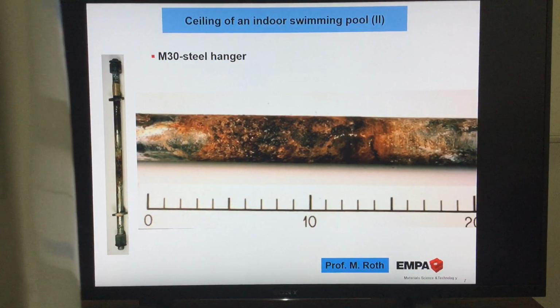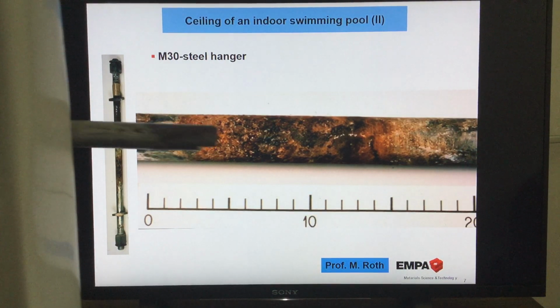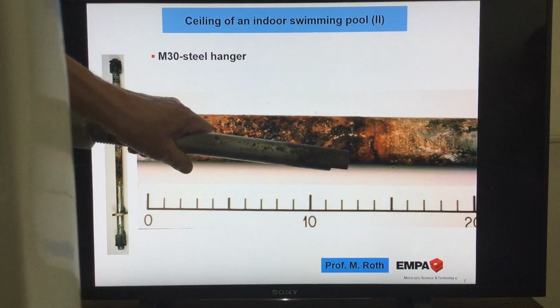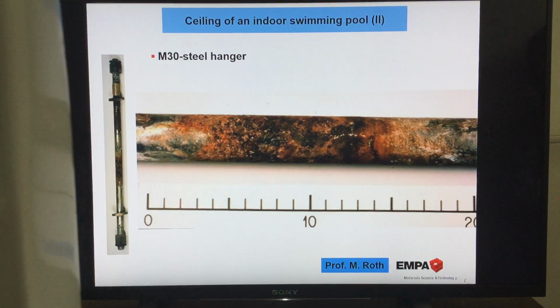Now that is at higher magnification, and I even have this component with me. Look at this here. It has a thickness of 30 millimeters, and it's heavily corroded, isn't it? And it looks really crazy and dangerous. And when you compare this, especially with the austenitic stainless steel which we investigated before, the Uster case, from outside it looks really heavily corroded, crazy, and we have to be afraid.